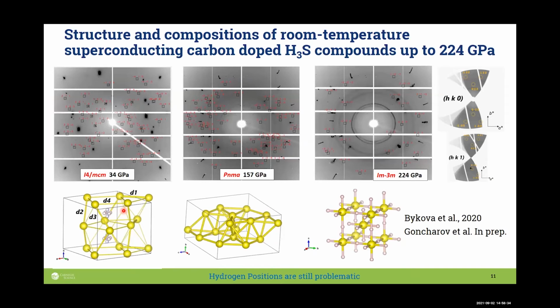Yet another result is experiments on carbon-doped H3S compound. This appeared to be a very interesting part of the investigation just recently, one year ago, where that kind of material was reported to be a room temperature superconductor. In the work which I present here, we determined the structure of these materials at different pressures, just using single crystal diffraction, as you can see here. What is important is that without single crystal diffraction, you cannot really determine where the positions of the atoms are, except maybe for a simple structure, which is the cubic structure of H3S. However, determining where the hydrogens are remains a very important problem, and it cannot be done very accurately even with single crystal X-ray diffraction.